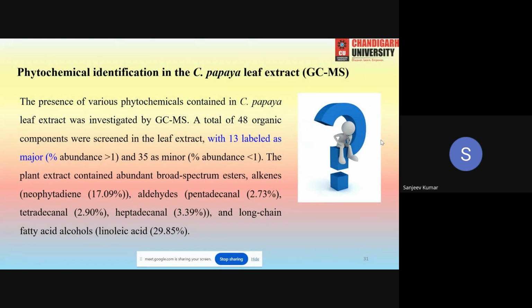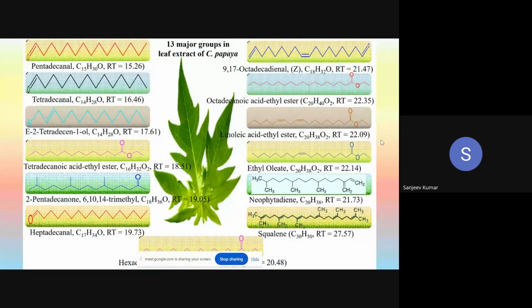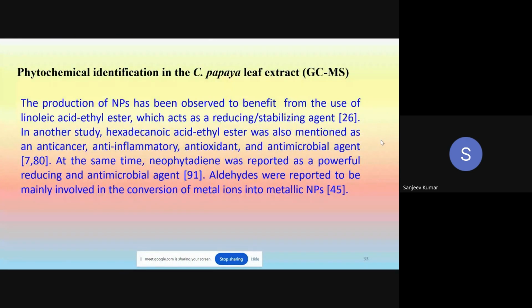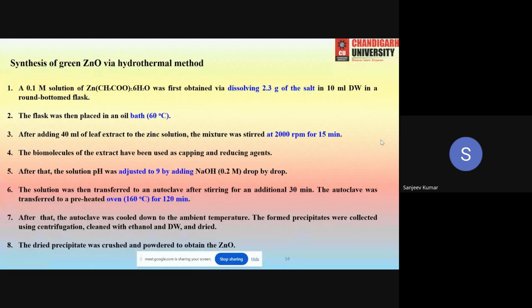In GCMS, we can easily identify what the papaya extract mainly comprises. Is it a reducing agent, a capping agent, or something else? So while synthesizing green nanoparticles, you first have to take care of the GCMS. These are some of the phytochemicals identified in the GCMS. After GCMS identifies a number of stabilizing agents, capping agents, flavonoids and antioxidants, you can start the synthesis process.